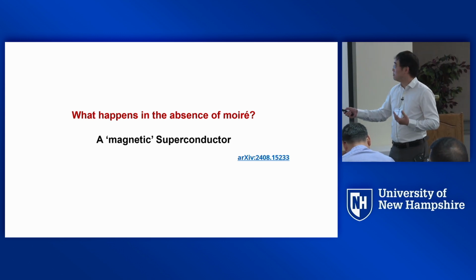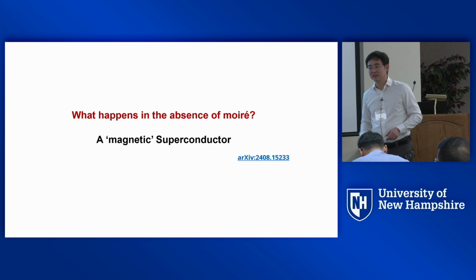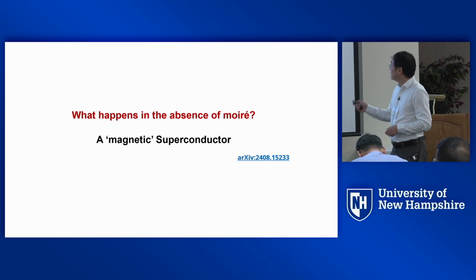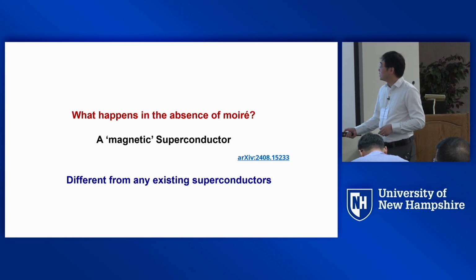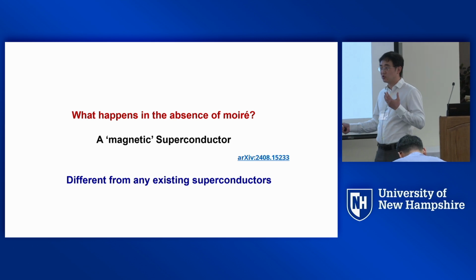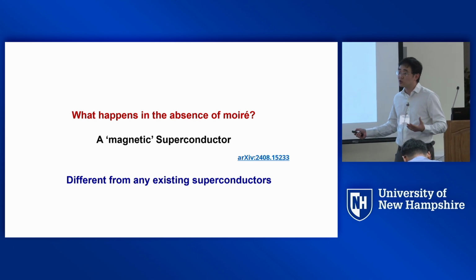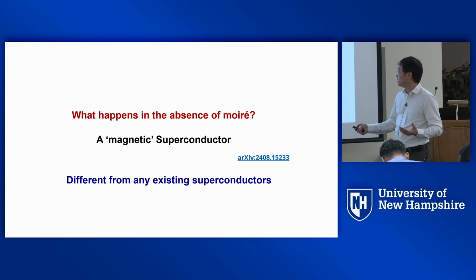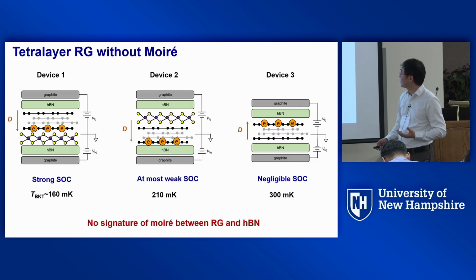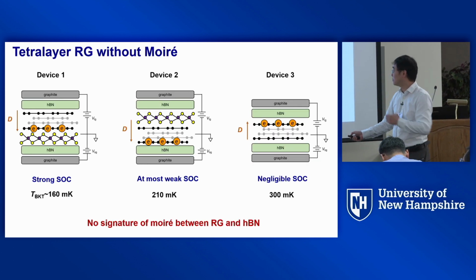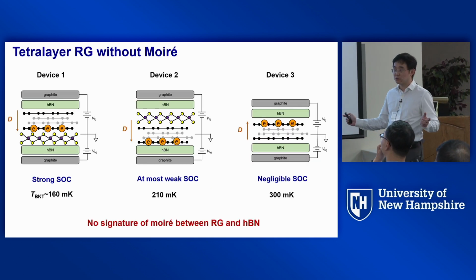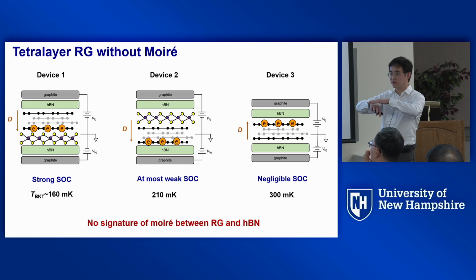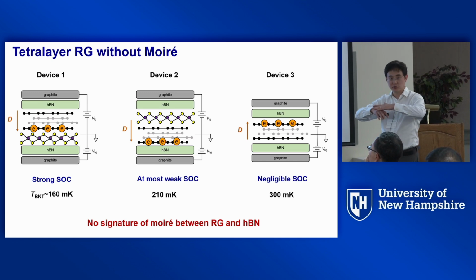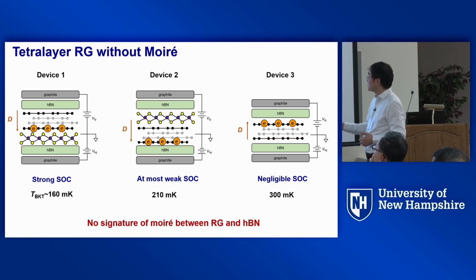And it's actually somewhat a magnetic superconductor, to fit the theme of this workshop. And we think phenomenologically, this superconductivity is different from any superconductor that we can find in the literature, for the following reasons. As I said, there's no Moiré. There's no signature of Moiré between graphene and hBN, so we have some big twist angle between graphene and hBN. And we have 3 devices.